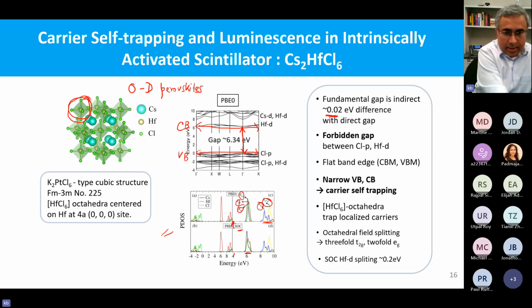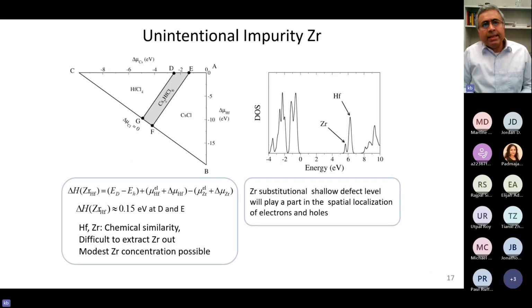And also, like I said, since we have hafnium, it's important to include spin orbit coupling. Although in our calculation we saw spin orbit effects were there, they did not create a very big difference. So without spin orbit, the calculations would also be pretty accurate. Anyway, then let's talk about zirconium.